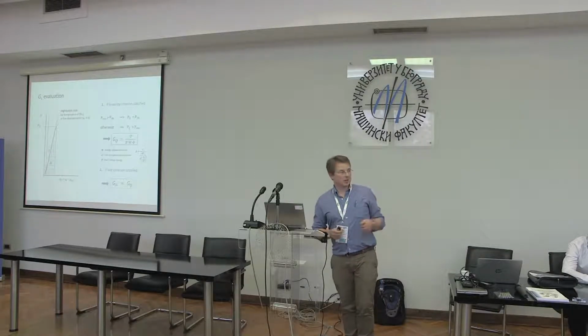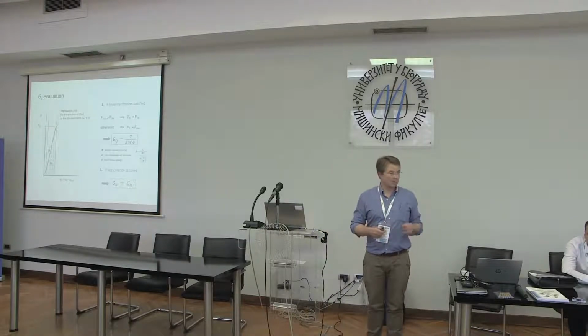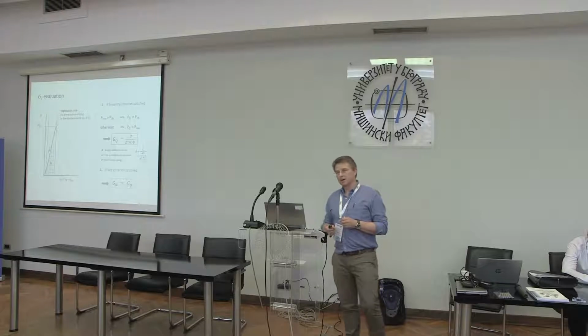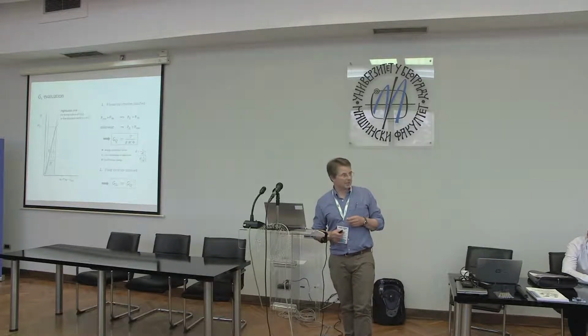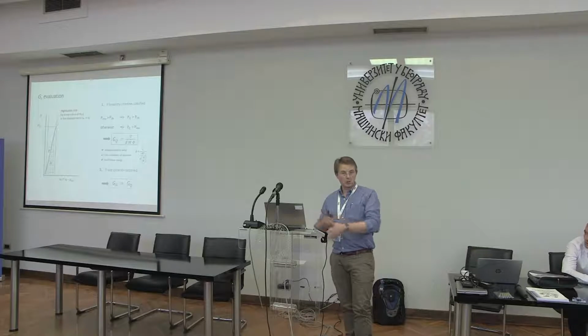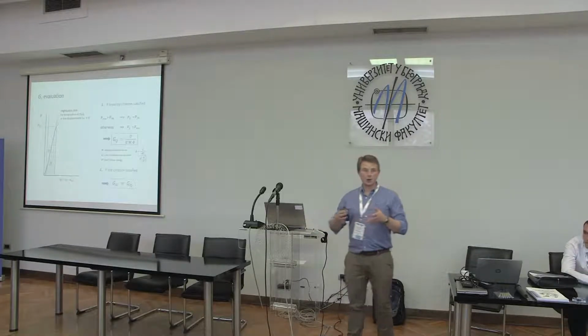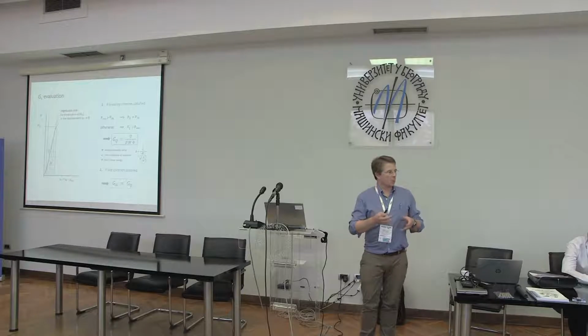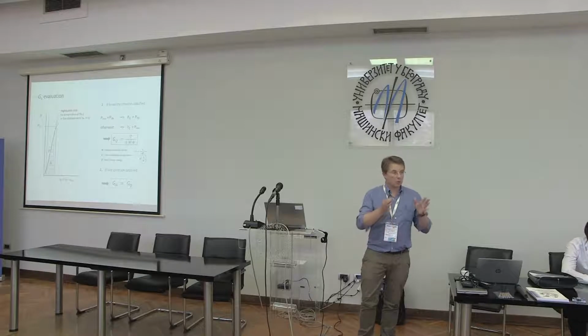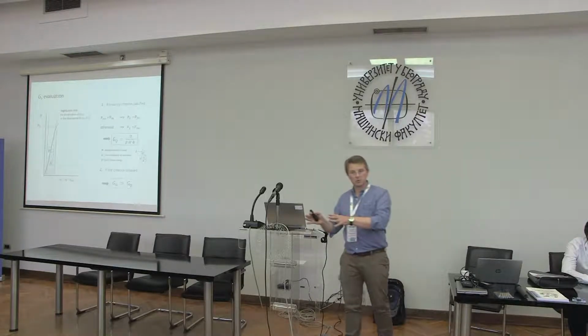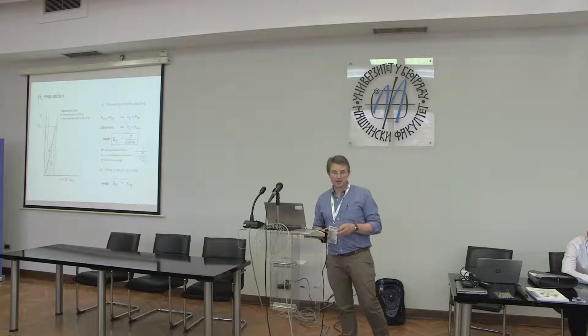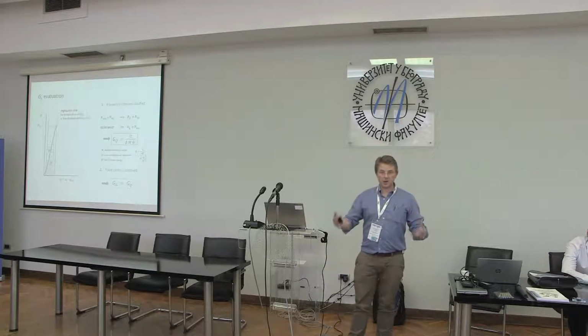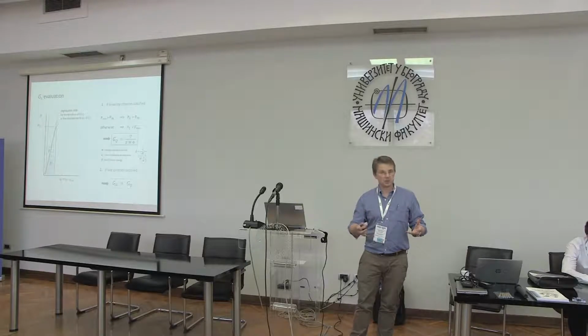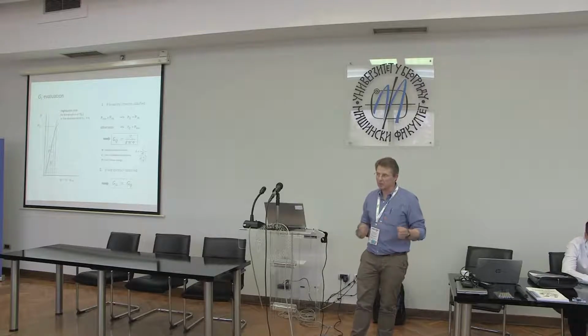So it's very much still an area that the technical committee is working on. There's some very good work going on, for example, by Francesco Baldi in Italy, using things like load separation criteria to try to get a better physical understanding of which polymers will and won't pass LEFM fracture conditions, which will be suitable for LEFM and which will be suitable, for example, for J testing a priori. So before you start, with a relatively simple test method, it'll tell you where you are in the whole range of validity. That's something that's going on at the moment.